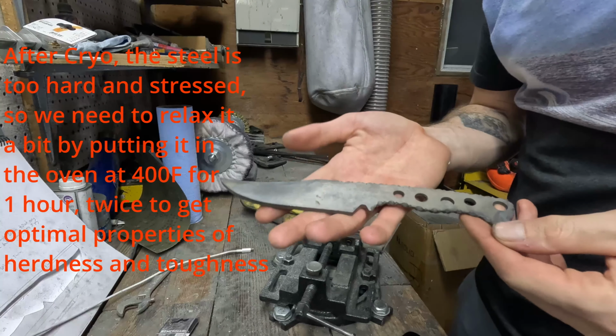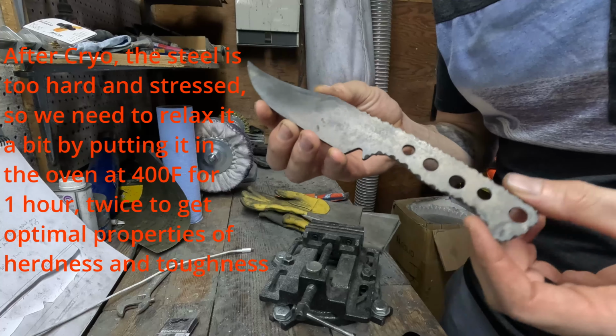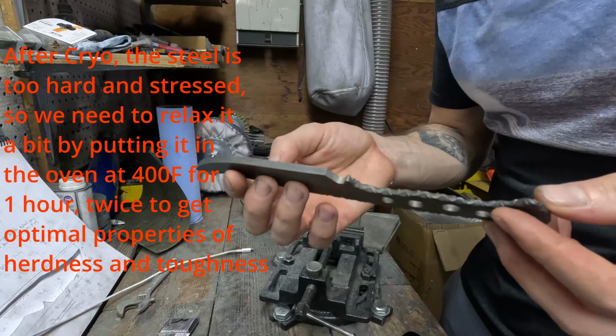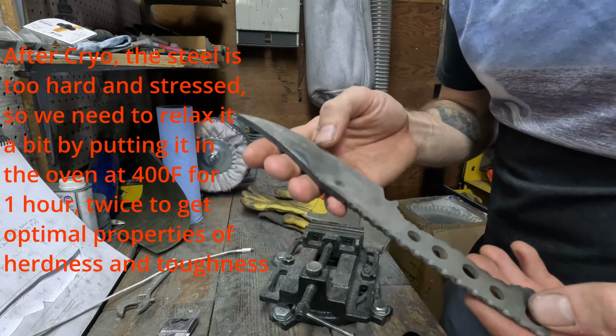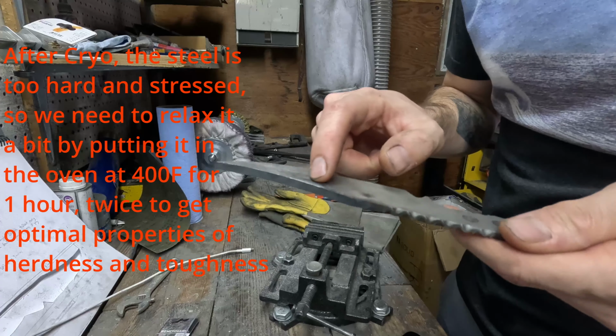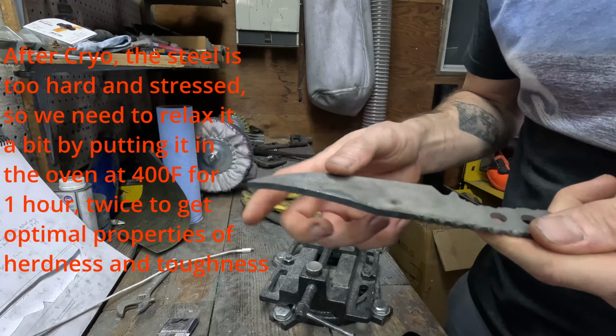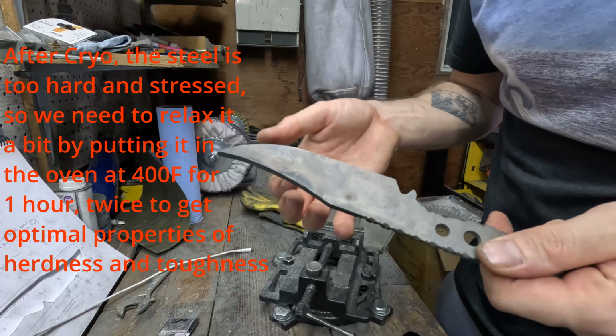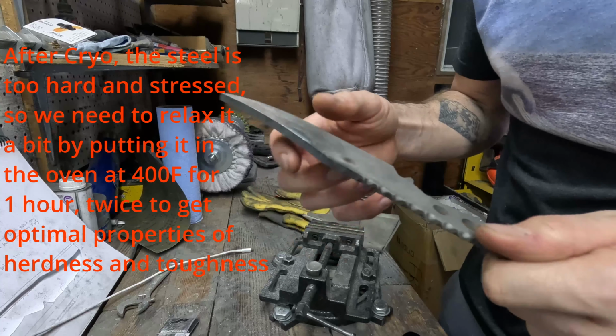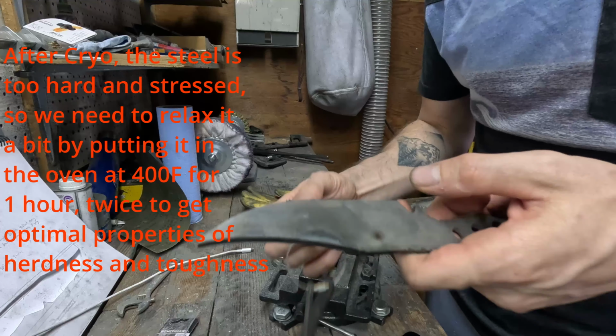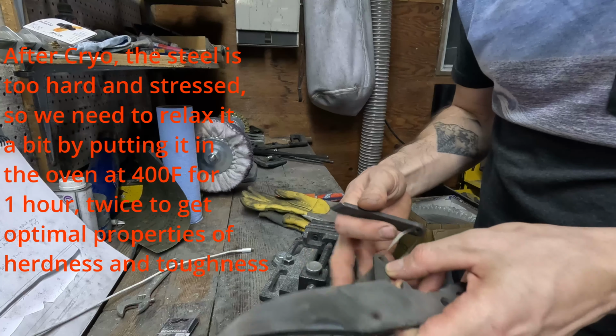Cool, so the knife came out of the heat treatment, liquid nitrogen, and then tempering in the oven. Looks pretty nice. We can see there's a bit of decarb here, but it doesn't matter. We're going to grind that swedge. And the rest of the blade heat treated really well. Now we can test the hardness.